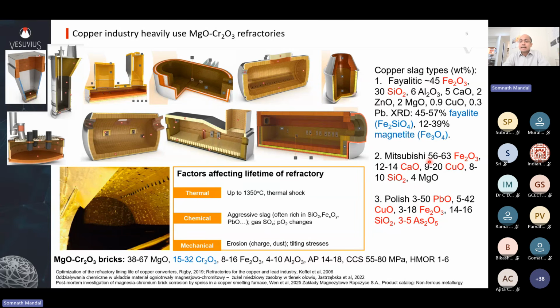And then in Poland, due to the nature of the ore, they have a lot of lead content, and they have a different process also in one of the plants, direct to copper process, where they charge directly copper-lead-iron alloy into the converter, the Pierce-Smith converter, and you end up with a very corrosive lead-rich lead-copper-iron silicate slag. And these slags are highly corrosive.